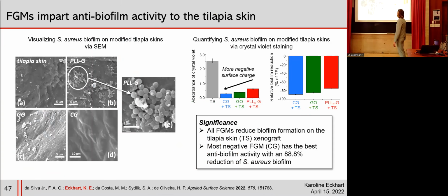And we found that tilapia skin, as expected, has a large amount of biofilm, which was quantified by crystal violet stain, and that all of the FGMs, regardless of their surface charge, actually reduced the biofilm formation on the xenograft models. But the most negative FGM, clay and graphene, was the most successful at reducing biofilm formation on the tilapia skin. It resulted in an 88.8% reduction in biofilm relative to tilapia skin on its own. So overall, this result told us that the negative FGMs could be a really useful application in wound dressings as a way to repel bacteria without having to use an antibiotic and have that risk of potential antibiotic resistance.